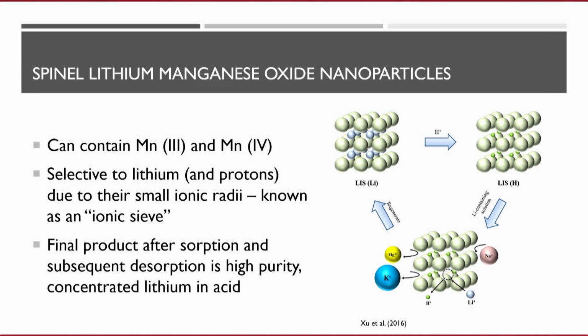What we then do, so now I've got a pile of basically a black or dark brown powder, you take that and you put it into an acid, and it ends up that the only thing of importance in a brine that can fit in those spaces besides lithium is protons, H+, the acidity. So that's what we call the protonation step. As you go on the top from the left to the right, now the protons, those smaller green spheres, are in there. And now you have a powder that you can stick into a brine and selectively recover lithium. So that's what you see on the bottom. We take this material, put it in a brine, and again, you can see all the things being rejected that we don't want. Sodium, magnesium, potassium, and others simply can't get inside the structure.